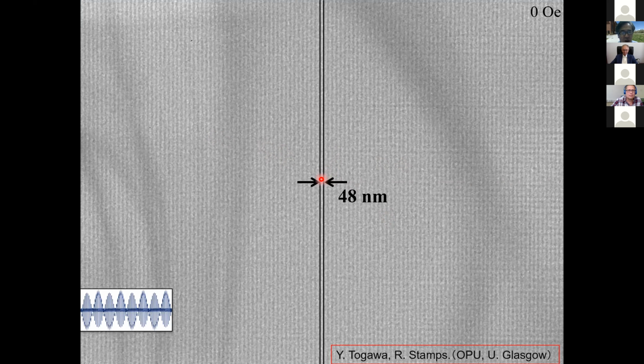When you look at these lines, you can find these lines are perfect. There are no branches, no diminishing, and the separation is 48 nanometers, perfect. This means that this spin system is never influenced by the defects of the crystal or magnetic defects. They are never influenced by these defects. Why? This spin system is so robust.